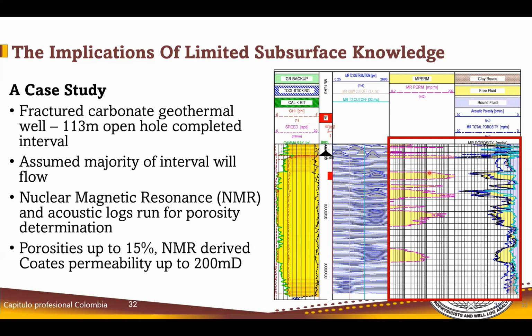And that's represented by this track here, this yellow shading. As you can see here, we have areas of large pores, lots of permeability, and areas of small pores, low permeability. And then it relates to your movable porosity, the yellow shading here, representing porosity that can potentially move. So what we can see here is permeabilities up to about 200 millidarcies, porosities to about 15%.